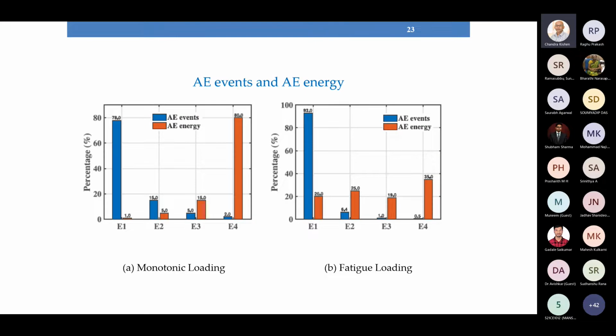Here we see again the difference through these bar charts, wherein the blue ones indicate the percentage of the events, that is the microcracks, and the orange one is the energy. What we see under monotonic loading is nearly 70% of the events are formed initially, but the energy is very low. That means at the beginning, a lot of microcracking does take place, but the magnitude of energy release is low. But at final failure, the higher energy acoustic emission events are generated, leading to the final failure.